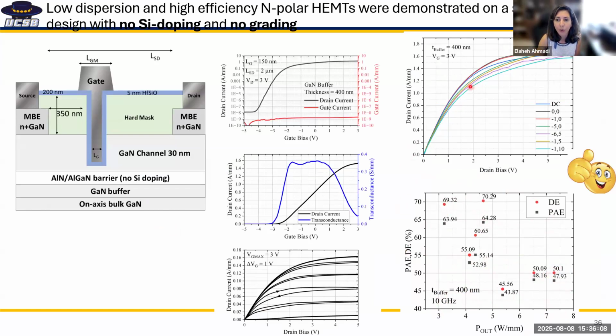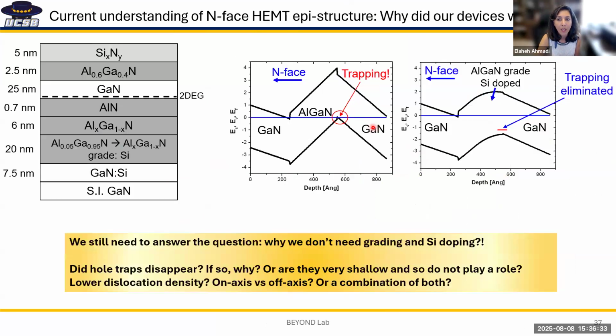And the pulsed IV showed a little bit of current collapse, but nothing too bad. And again, I want to emphasize that this is with a simple EPI structure with no silicon doping, no grading, and nothing. And basically, we were able to get devices as good as people have demonstrated on other more complicated EPI structures.